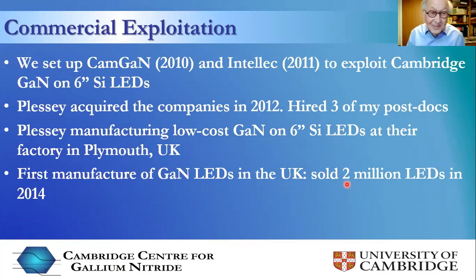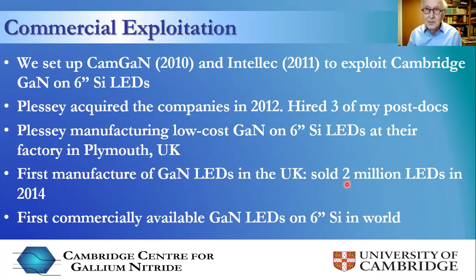So we did it very quickly, and then Plessey manufactured low-cost gallium nitride on 6-inch silicon wafers at their factory in Plymouth. They reckoned the cost reduction was a factor of 5 compared with growing on sapphire or silicon carbide. This was the first manufacturer of gallium nitride LEDs in the UK, and they sold 2 million LEDs in 2014, to companies like GE to put in their light bulbs, and then companies around the world put them in their light bulbs. It was also the first commercially available GaN LEDs on 6-inch silicon anywhere in the world.